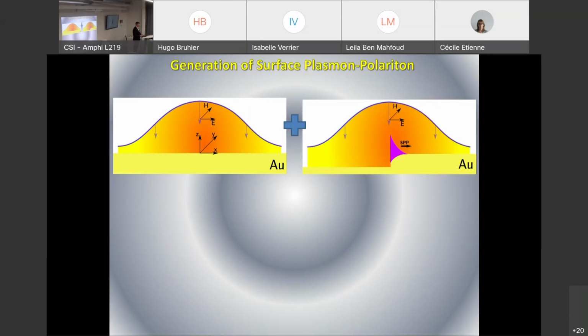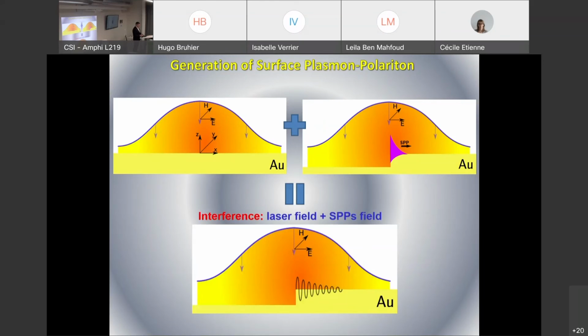And collective motion of these electrons and propagation of the corresponding wave results in the propagation of the so-called surface plasmon polariton, propagating along the interface between two different media. So this surface plasmon polariton interferes with the incident electromagnetic wave, resulting in the modulation of heating of the sample surface. So the absorbed intensity is redistributing across the surface, and that's resulting in modulation of heating.